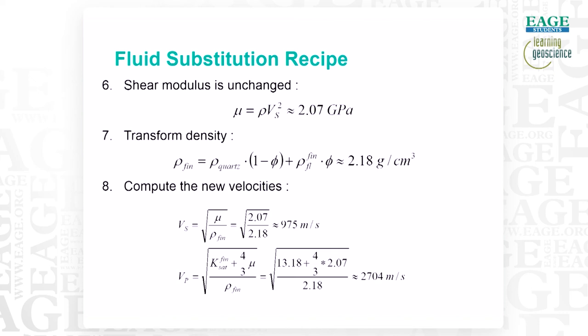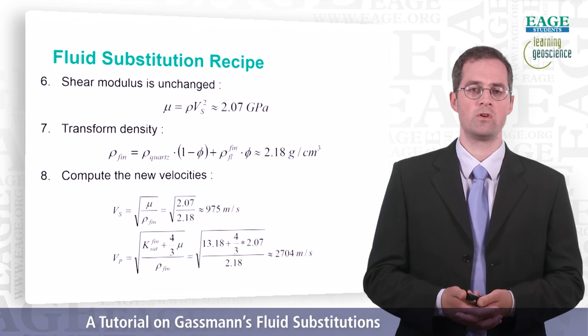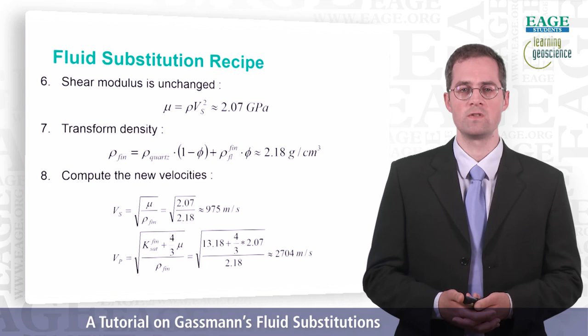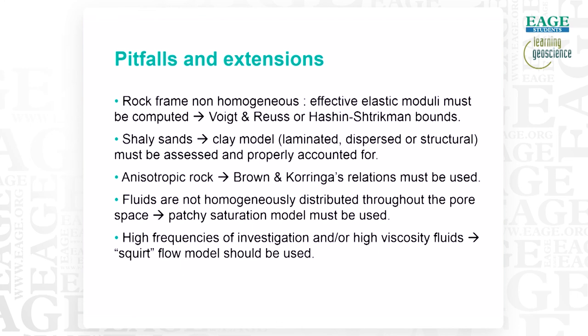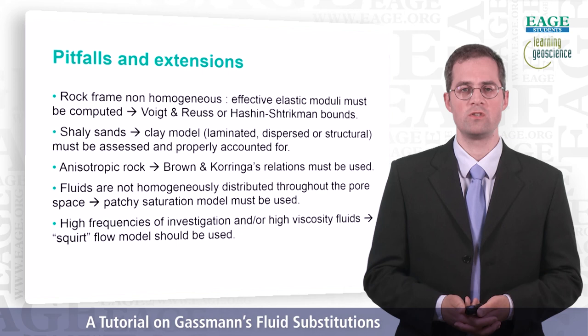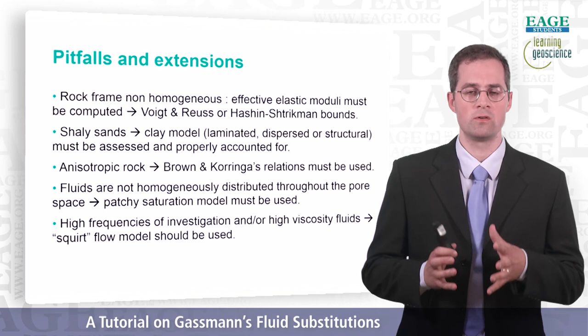And then the P wave velocity, we use the new saturated bulk modulus that we have computed using Gassmann. The shear modulus is the same as before, and the denominator is the new density that we have computed together. And in the end, we get a velocity of 2,704 meters per second. So we have been able together to apply this Gassmann's methodology, which is quite straightforward actually. But again, it's only valid if your basic assumptions are valid and met.